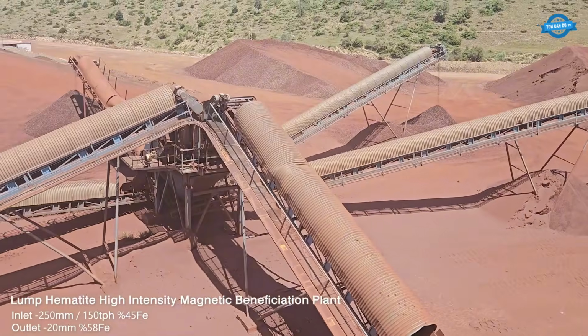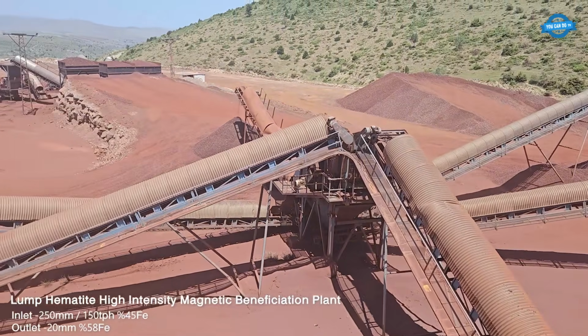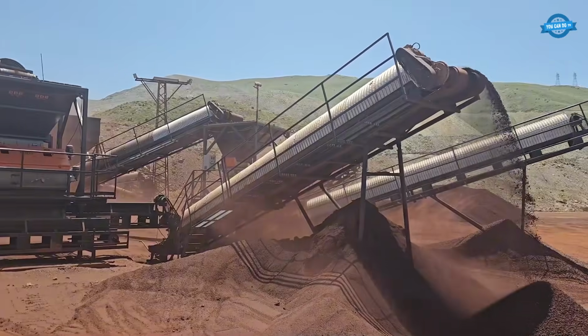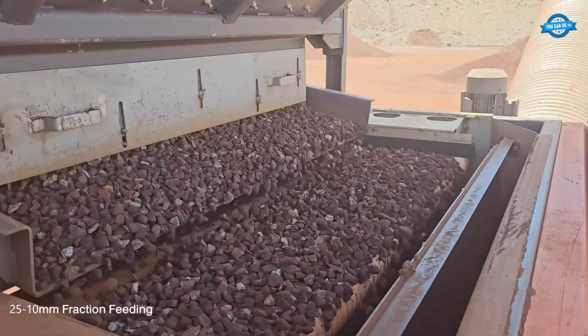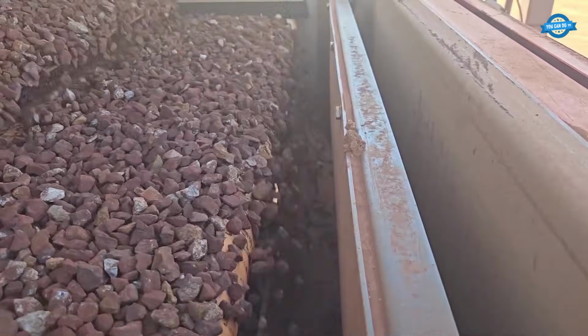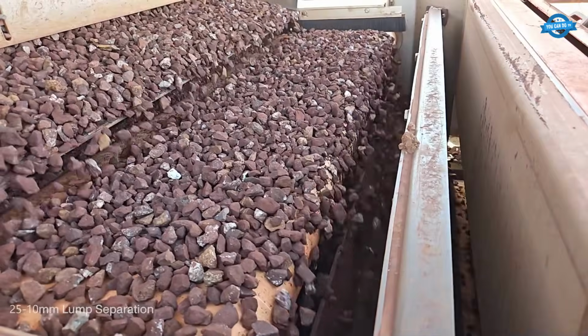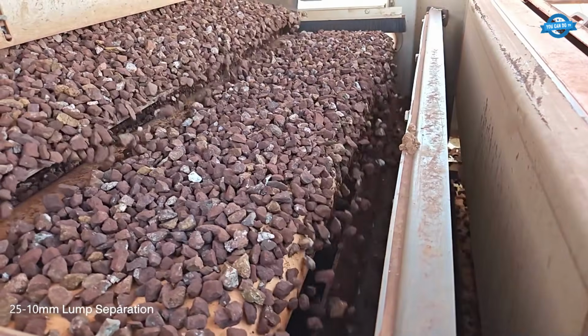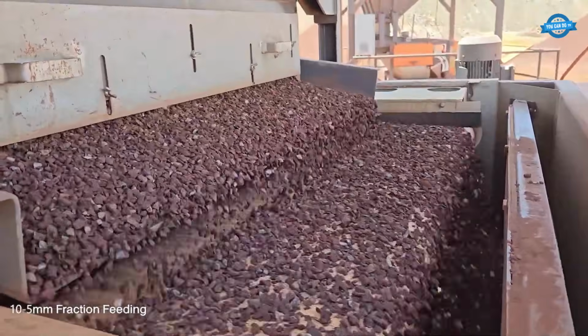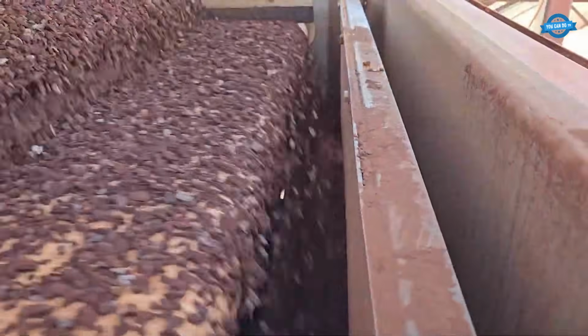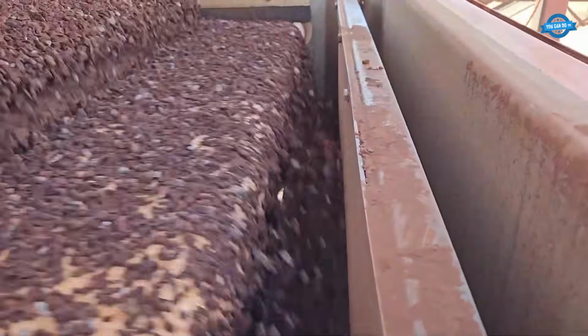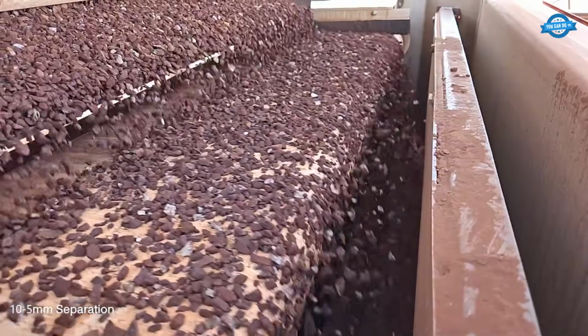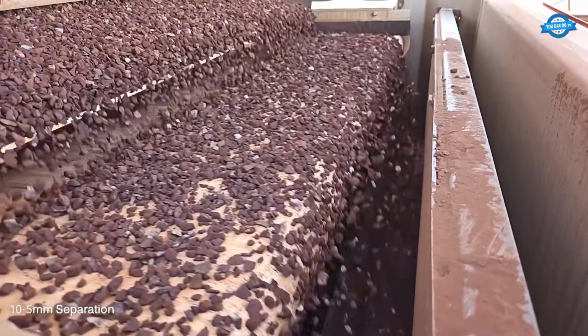Meet the plant whose entire job is to remove everything you did not order. The feed here shows up at around 45% iron, respectable, but not the grade a steel mill will hand over premium cash for. The plant runs the material through crushers and screens, splits it into size fractions, then sends each fraction past a series of high-intensity roll magnets running between 1.1 and 1.5 Tesla.